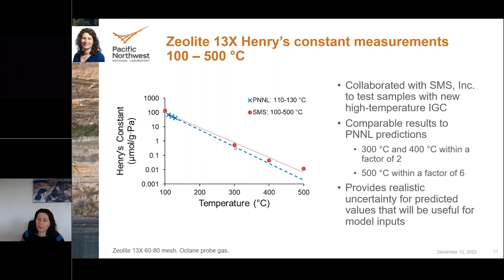So for example, at 300 degrees Celsius and 400 degrees Celsius, the measurements were within a factor of 2 of our predictions. And then at 500 degrees Celsius within a factor of 6. So this has twofold implications. One is that it provides some realistic uncertainty for what your predicted values might be. And that's useful for model inputs, so you have a sense of what the end members are and what you can expect.